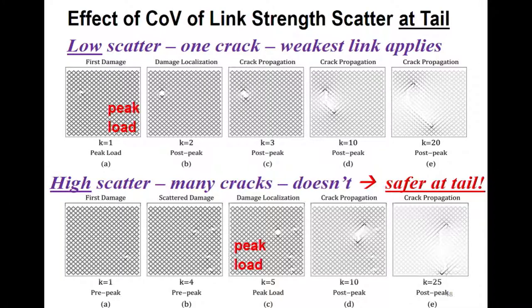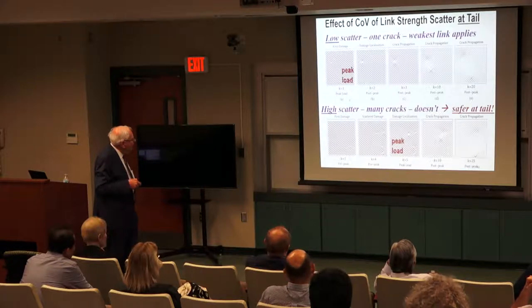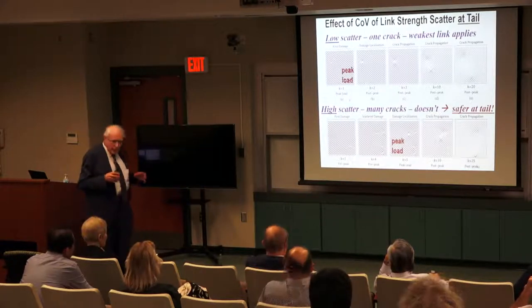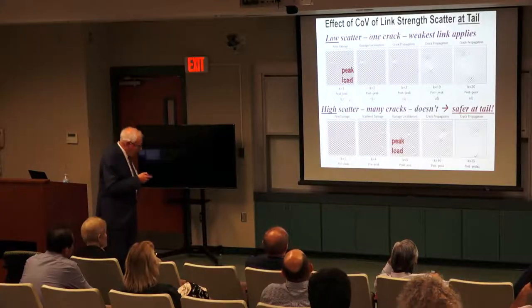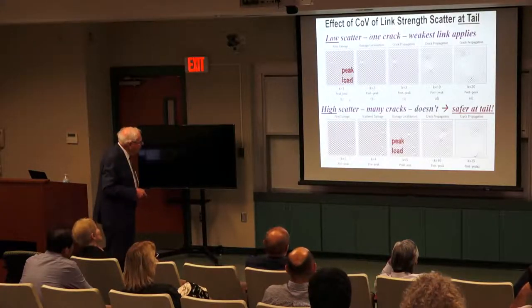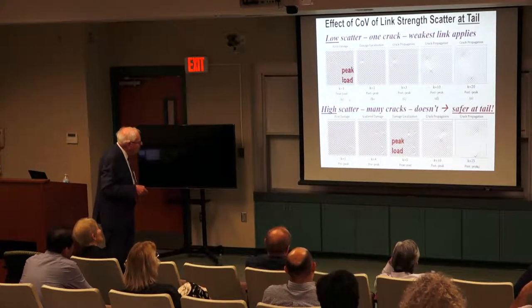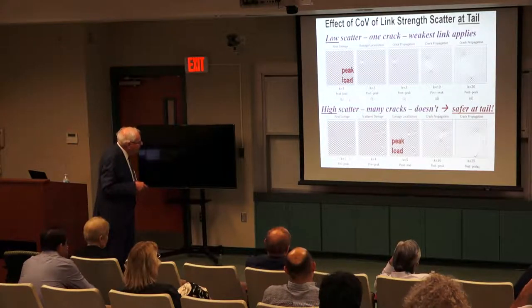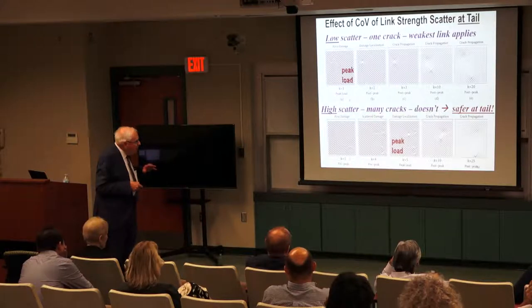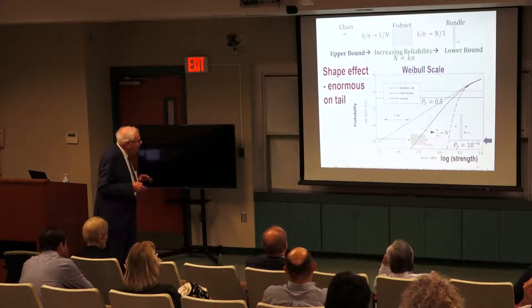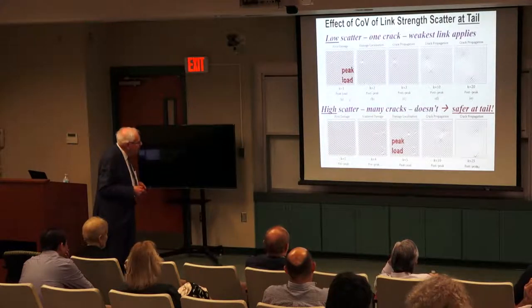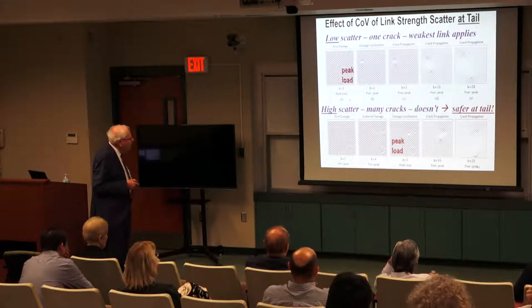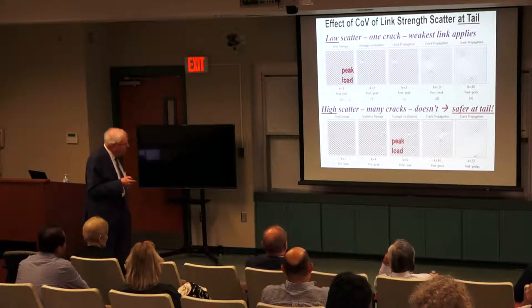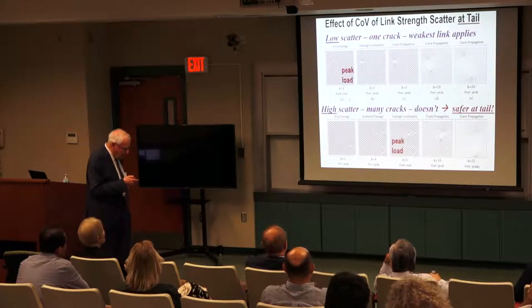At low scatter, the peak load occurs very early, typically at the first element. If there's no scatter, a perfectly positive geometry would fail with one link, that's it. But as the scatter increases, peak load happens after much damage, as you see here. These are actually simulations of this fishnet you see here exactly. So high scatter may weaken the material in the mean, but can make the tail very much safer. So this is a very useful property to know. Sometimes scatter is good actually in these materials. We should not aim at the most homogeneous structures.